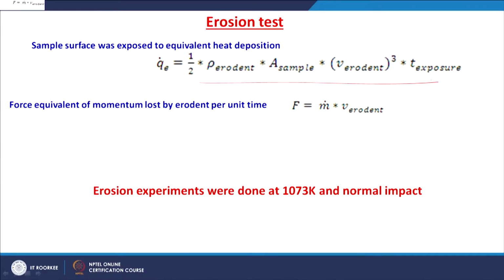So, the sample surface was exposed to equivalent heat deposition as given here, and the force equivalent of momentum lost by erodent per unit time was also calculated. But erosion experiments were done at 1073 Kelvin, that is 800 Celsius, and normal impact. So, this selection of 1073 K is also based on the limitation of the erosion test equipment.